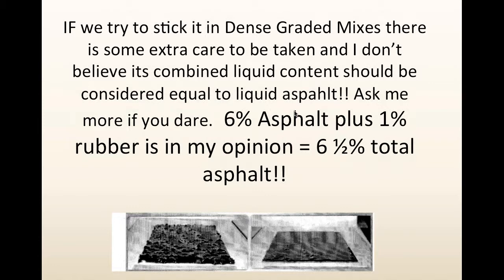I threw this in here. Some of the states, I'm sure, are adopting this asphalt rubber blend in dense graded mixes. The universal mixes that we talked about originally, the asphalt doesn't quite fit inside the matrix. So when you go to using a dense grade mix, you should look at a finer grade rubber, maybe even terminal blend, not necessarily.